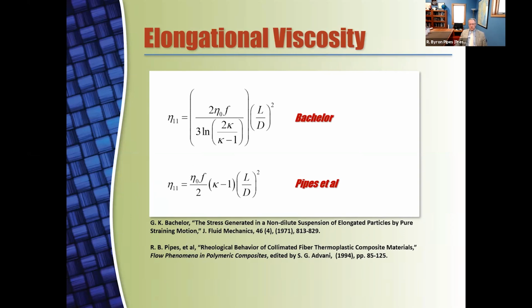It goes substantially high. And typically we have long aspect ratio fibers. We have aspect ratios of at least 1,000 if they're going to do a good, efficient load transfer. And so it became very clear that this viscosity term was predictable, but that it was going to be quite large. And the two publications that I call out are the ones that Batchelor did and our own publication summarized in a book that was edited by Advani. I'll mention Advani again in a moment.